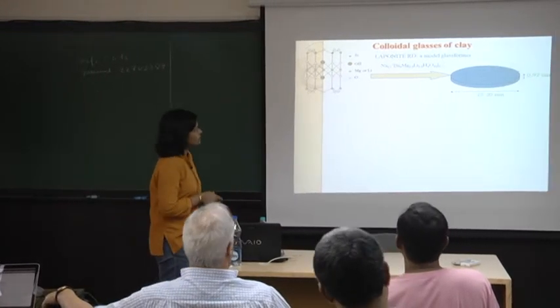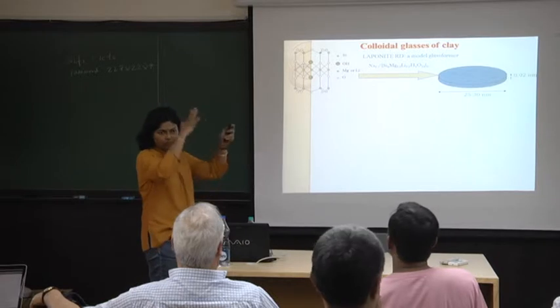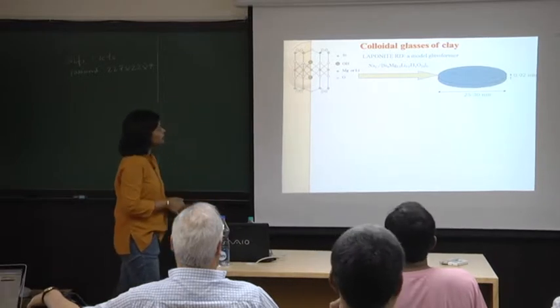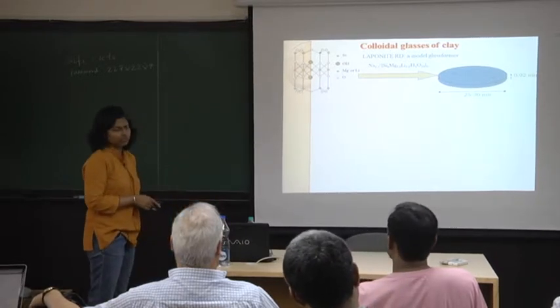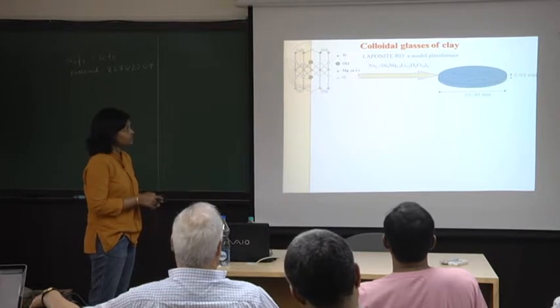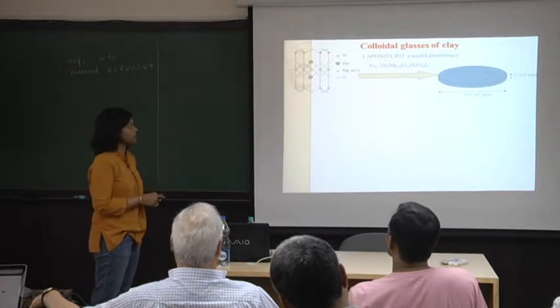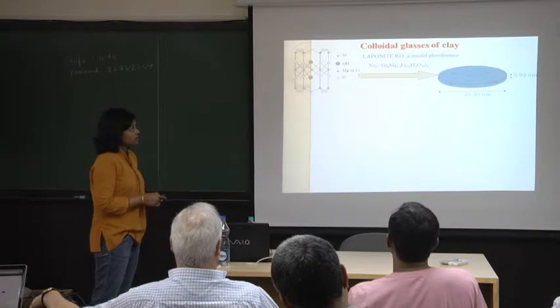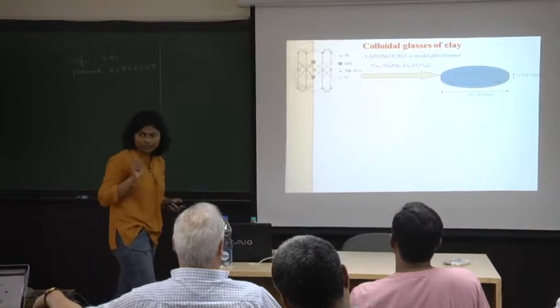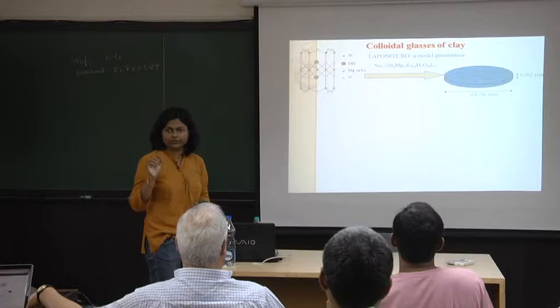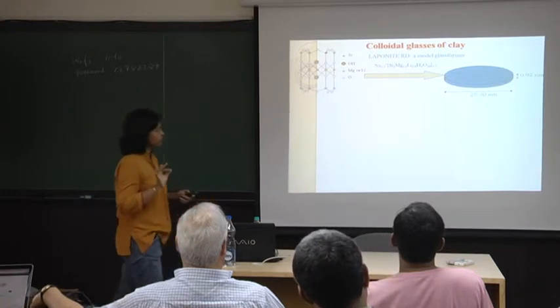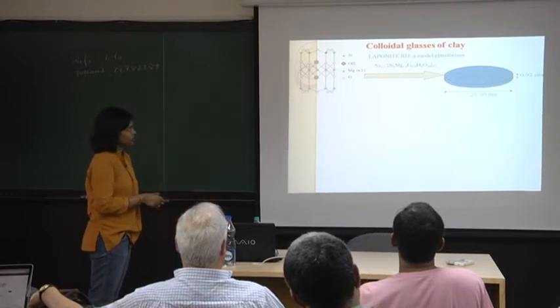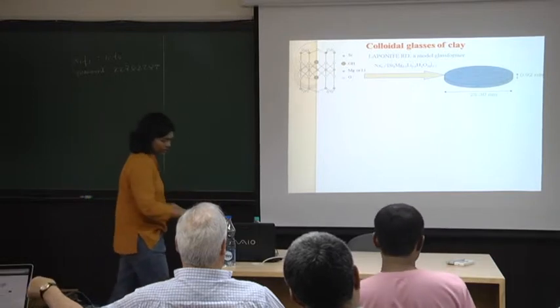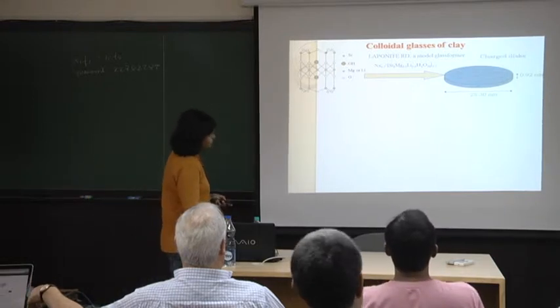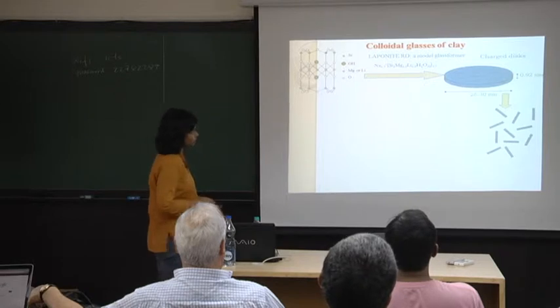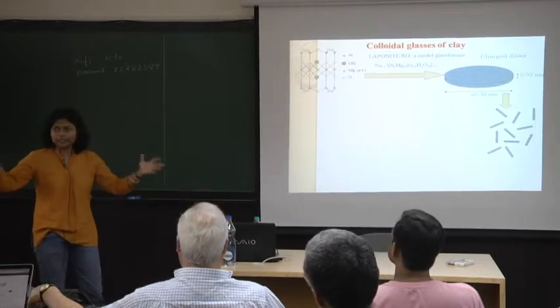When you throw this disk in water, it starts releasing sodium ions which form a big charge cloud around the disk, leaving a negatively charged surface of the Laponite particle behind. The edge is not always negative. In our case, it is very weakly positive because of the protonation of certain charge groups on the edges. So when you throw many of these particles in water, you will have a collection of randomly oriented disks.